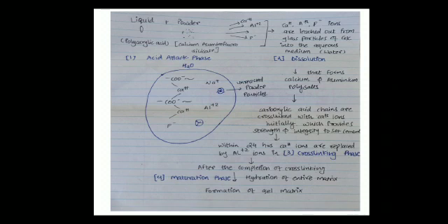So calcium, aluminum, and fluoride ions are leached out. This is called the dissolution phase, and these ions form polysalts together, and they react with the carboxylic acid chains which are present in the liquid. Here we can see carboxyl groups reacting with the calcium salts and creating cross-linking in the first phase.